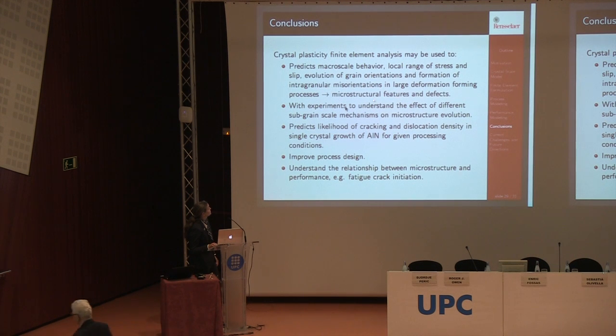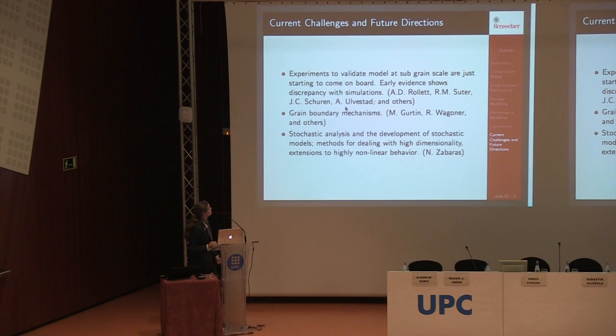This analysis can be used to predict macroscale behavior, local range of stress and slip, evolution of grain orientations and formation of intragranular misorientations in large deformation processes, so we can predict microstructural features and defects. With experiments, we can learn about the effect of different subgrain scale mechanisms on microstructure evolution, predict likelihood of cracking and dislocation density in aluminum nitride. It can be used for improving process design. We also used it to understand the relationship between microstructure and performance. Just some things that I'm really interested in.